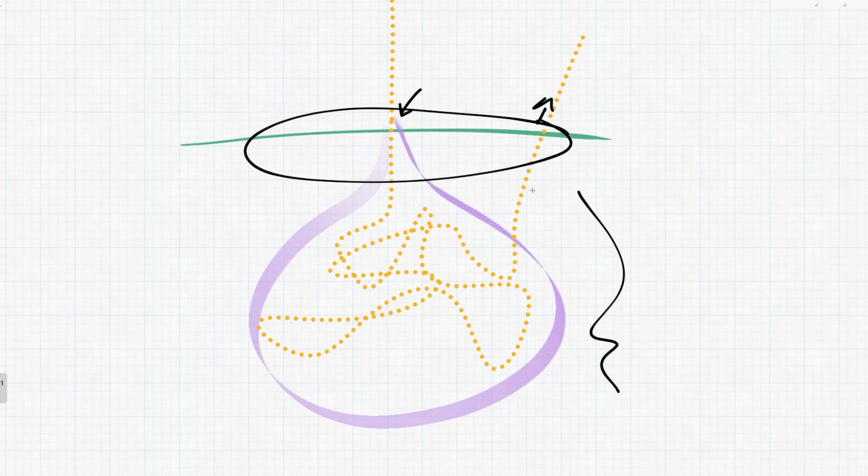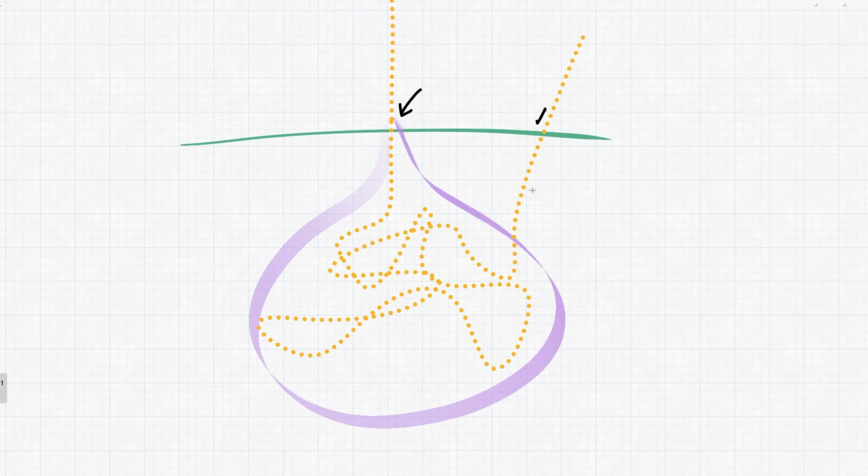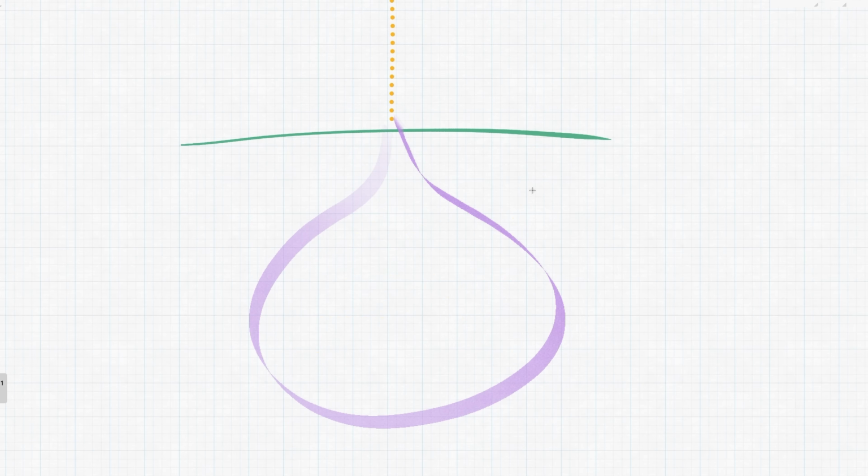And so there's kind of an area of blurring where our nicely focused electron beam blurs out due to this interaction volume. So the key insight to transmission electron microscopy is that if you make the sample really thin, well, there's just not a lot of material there to interact with. And so the electron beam will either pass straight through it, or it'll interact with something in the sample, but still come out essentially parallel to the initial beam entrance. And so now our interaction volume, we have a much smaller area. And so we get much better resolution on a TEM because there's just not as much material to deflect or interfere with our electron beam.